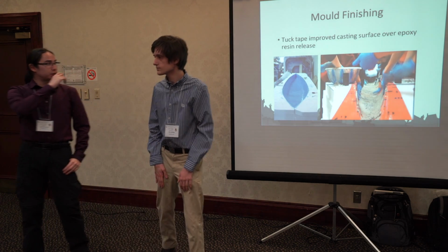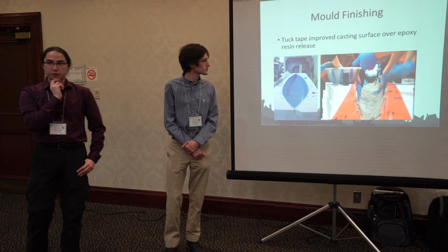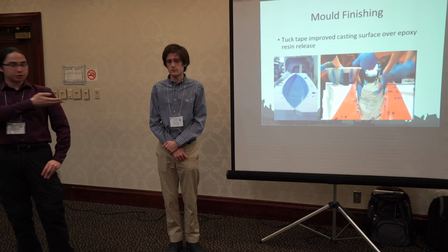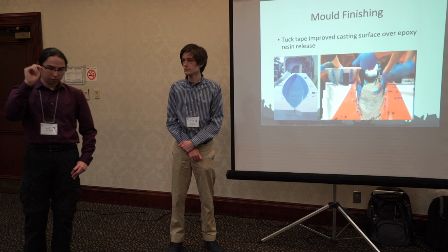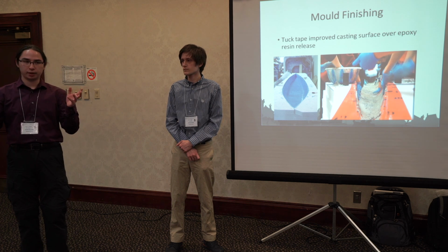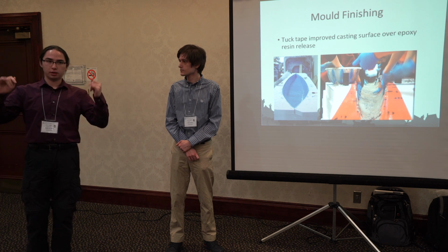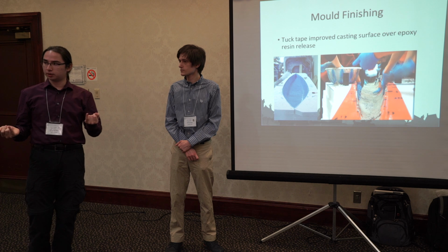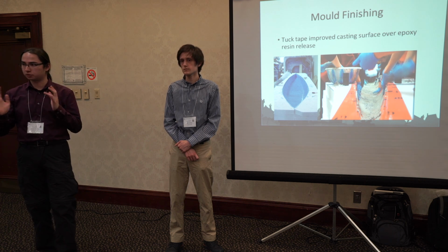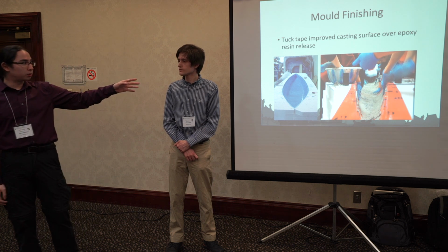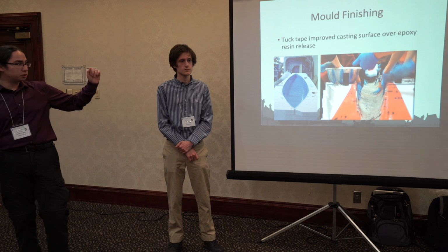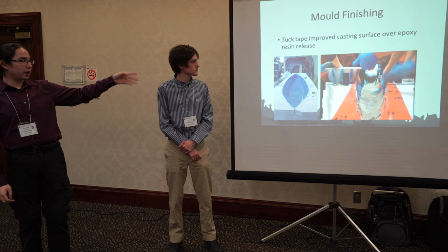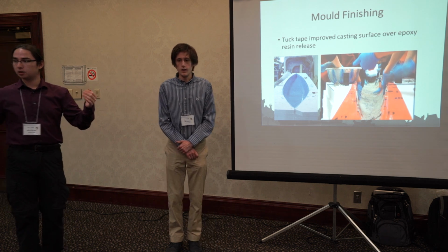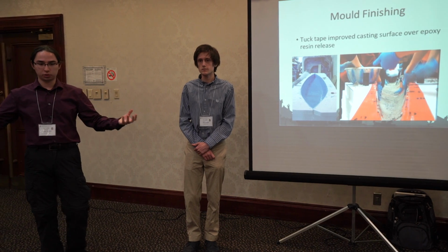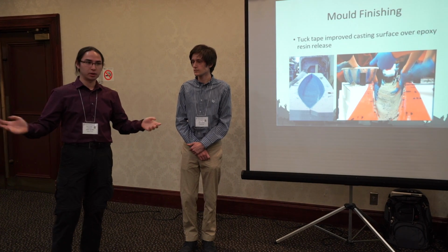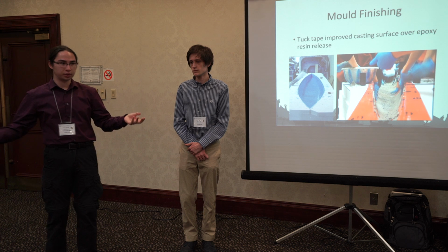So mold finishing is another place where we've tried to drastically improve our process. As Dale mentioned, the reason we switched from a male mold to a female mold is that when you cast the canoe, the outer surface that doesn't touch the mold tends to be much rougher and have surface textures. So with the female mold, we've switched. In the past, we've used shrink wrap. We've coated the entire mold in shrink wrap, heated it, and it shrinks down, and that creates a smooth casting surface for you to cast upon.